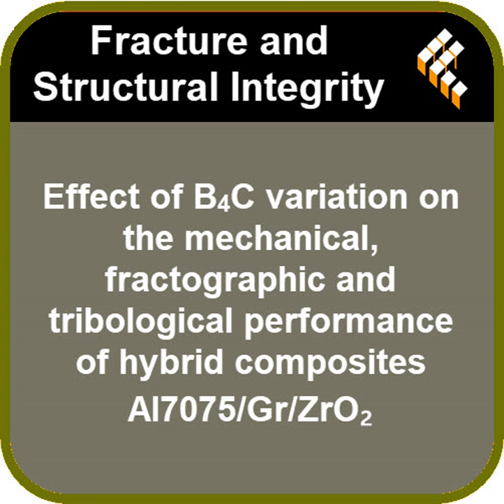Over a third less wear? What was happening on the surface to cause that? The surface analysis really showed that synergistic effect in action. I mean, the base alloy just got torn apart. Severe adhesive wear, deep grooves. But the composite had a much smoother worn surface. Minimal grooving. It's like it has this internal self-protection system. The B4C and the ZrO2 act like armor plating, resisting penetration. And the graphite is the lubricant. Exactly. The graphite is in there acting as this continuous solid lubricant, minimizing friction and stopping material from getting ripped away.